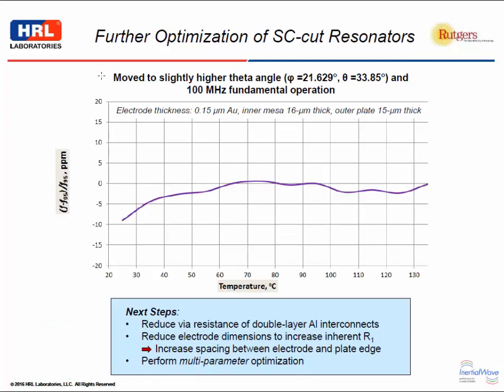Okay, so where do we go from here? The optimization of the SC-cut resonators needs to be addressed. We simply did a few things quickly towards the end of the program, and that was just to move to a higher frequency design, 100 megahertz, and change the theta angle slightly to see whether we could improve the performance. So we increased the theta angle a little, and we got this sort of FT profile. Still has some wiggles in it, but it's clearly got rid of the major activity dips.